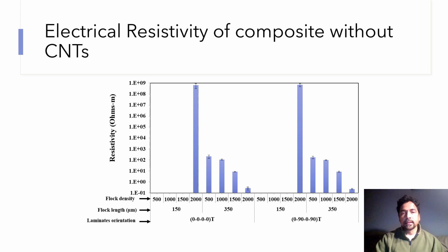I would like to show you here the resistivity values with and without carbon nanotubes. We wanted to achieve decent resistivity values without putting any carbon nanotubes. As you can see here, if you do not put any carbon nanotubes in the system for 150 carbon fiber length composites, you cannot pass current through the system for flock densities up to 1500 fibers per millimeter square. You can only send the current at 2000 fibers per millimeter square flock density in the case of 150 micron carbon fiber composites. If we take into account 350 micron carbon fiber composites, we can send the current even with 500 fibers per millimeter square. So 350 micron carbon fibers penetrate through the laminates, which will give us a good network even without any carbon nanotubes for both systems of 0/0 and 0/90.